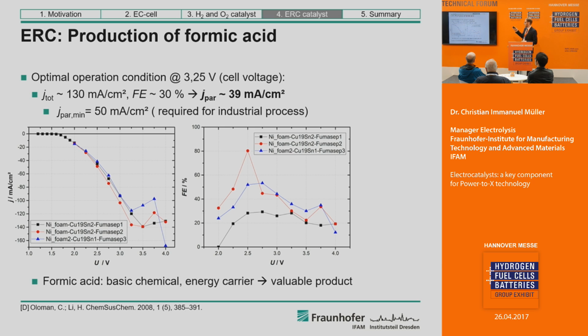And if we analyze the product we get during this reaction, we see that at the cell potential of 3.25 volts, we have a current density of 130 milliamps per square centimeter. And the Faradaic efficiency for producing formic acid is around 30%. So the partial current density which produces formic acid is around 40 milliamps. Some authors state that you need around 50 milliamps per square centimeter for industrial production of formic acid with this technology. So we are very close to this threshold for industrial production.